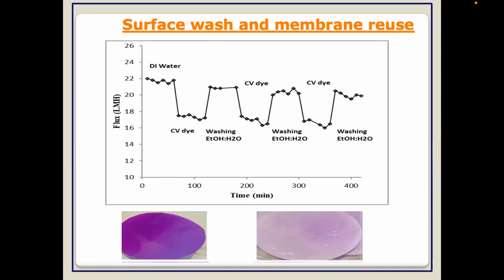Surface wash for membrane reuse. This membrane was used for crystal violet removal, and we washed it many times, to use it up to 400 hours. From this figure, it's clear that we can obtain the maximum flux production after each washing time.